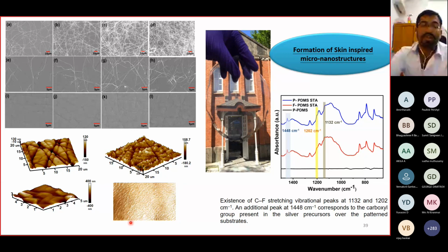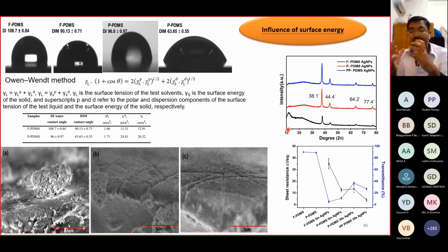We also characterize the surface energy values in order to compare the flat surface and the patterned surfaces. Here we can see the silver nanoparticle formation is quite good on the pattern structures. Why? Because it has very good surface energy. The flat PDMS surface energy is 12.91, whereas for the patterned PDMS, it is already doubled. So it's good. If your surface energy is high, you will have very good formation of your nanoparticles.